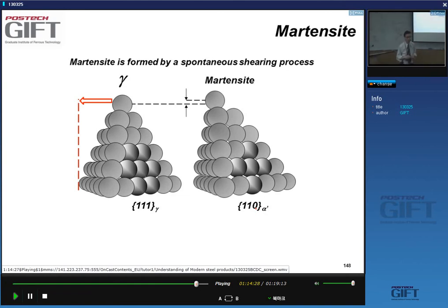And in fact, there's a family of steels called maraging steels, where, to make a part or to make the thermal treatment possible and obtain extremely high stresses, there is an intermediate step where we form very soft martensite. The way it's done is simply by having absolutely no or very little carbon in solution. So martensite is not brittle or hard. It's only brittle and hard if there is, in our case, carbon in solid solution, in supersaturation.